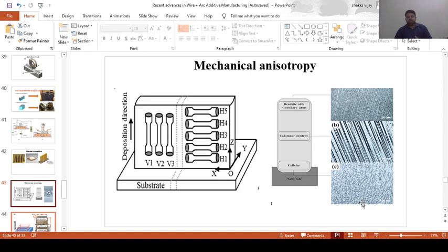So there is variable mechanical property, variable corrosion resistance property as well, and variable micro hardness and other things. That is generally based on what kind of grain morphology we have obtained. Generally we will get a mixed structure, not everywhere the same equiaxed or everywhere the same columnar dendrite. Everywhere it will be a different grain morphology, which will result in this kind of mechanical anisotropy.